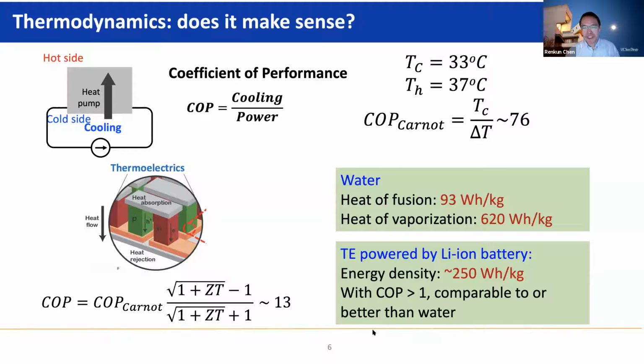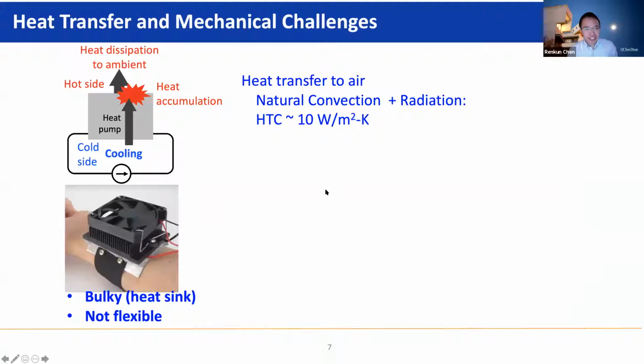So for example, if COP is 3, then you actually can get similar overall energy density compared to the evaporation heat of water. And as we know, water actually is always one of the best and most common heat transfer fluids for a lot of heat transportation. So if you are operating similar to or better than water, you are actually in good shape. And so obviously we would like to have a very high COP greater than 10, but this makes it possible using battery-powered thermoelectrics. So we think it kind of makes sense, but there are also other challenges, in particular heat transfer and mechanical challenges.